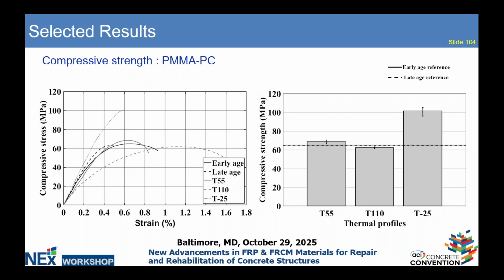I want you to focus on the right side. As you can see, there isn't much degradation when subjected to both 55 and 110 degrees Celsius. On the extreme negative temperature, the compressive strength increased significantly.